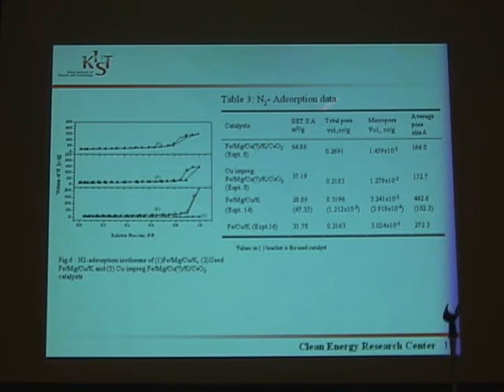This is the nitrogen adsorption curve. The BET surface area is around 64 for this particular sample, because here ceria and magnesia act as a structural promoter and hence the BET surface area is more. Then the copper impregnated has shown 37.19 and the magnesium promoted has shown 28.89 and so on.